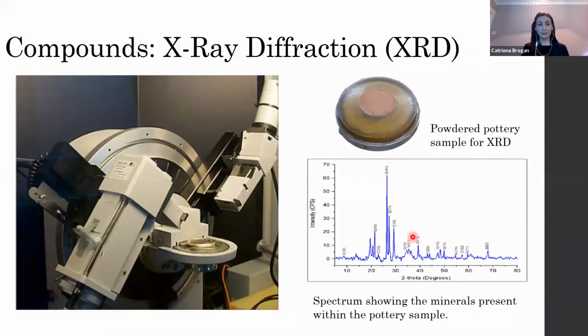Then we also used X-ray diffraction, commonly known as XRD for short. And this is something else that gives us the compounds. So basically, unlike the petrology analysis, in which you are analysing essentially a full, complete section of the pottery sherd, for the purposes of the X-ray diffraction, the pottery has to be ground up into a very fine powder, and then this is analysed with the X-rays. I'll not go into all of this because it's quite complicated and the science is pretty much beyond me half the time, but essentially it produces a spectrum along which we have the different minerals that are present within the sample.